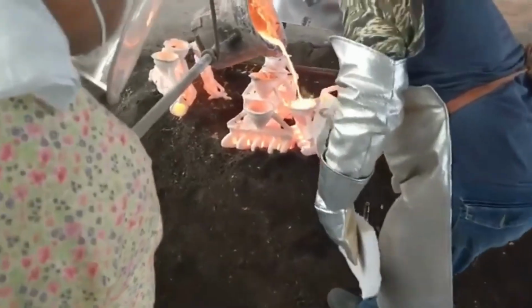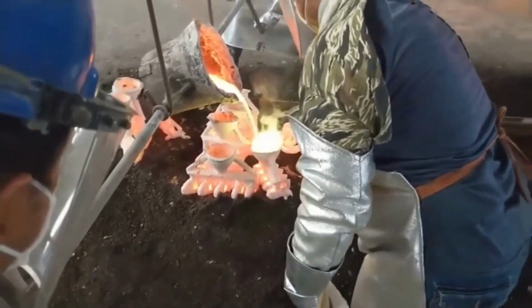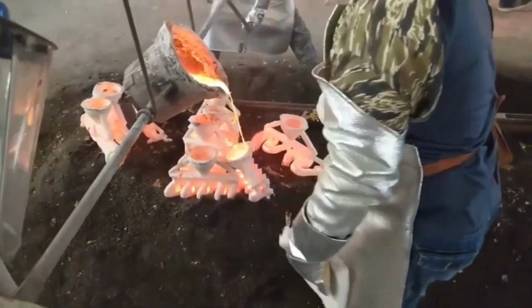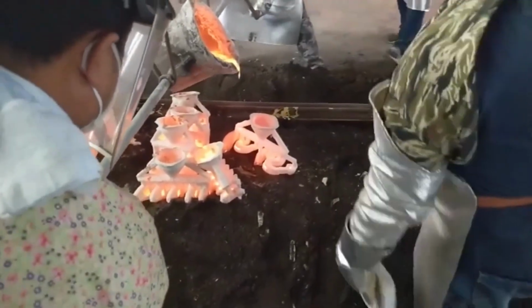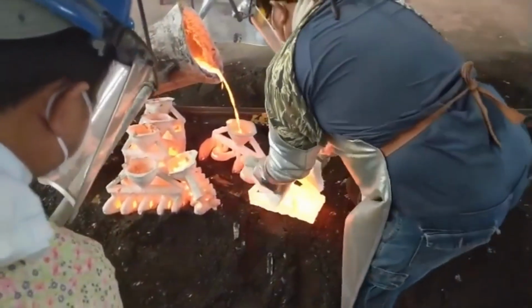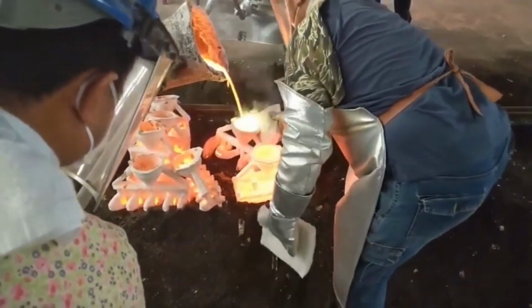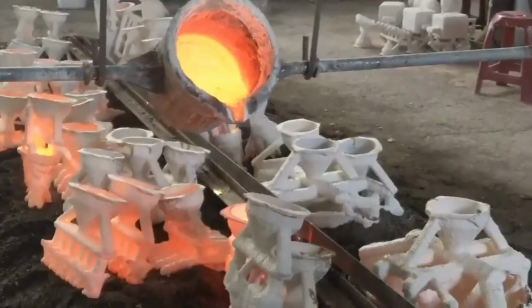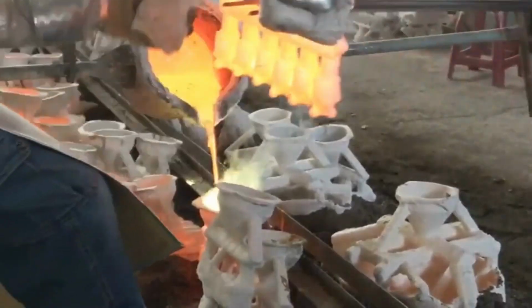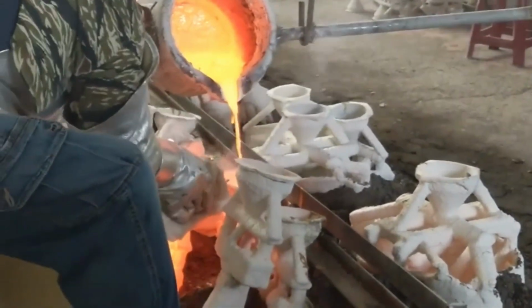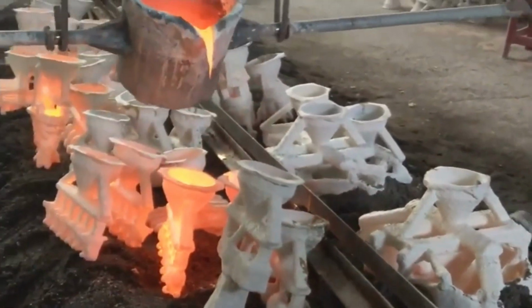Once the ceramic shell is complete, the wax is removed through a process called de-waxing. The assembly is placed in a high-pressure steam autoclave or heated in a furnace, melting and draining the wax from the mold. Following de-waxing, the ceramic shell undergoes high-temperature sintering, 700 to 1,100 degrees Celsius, which burns out any remaining wax residues and significantly increases the mold's strength.